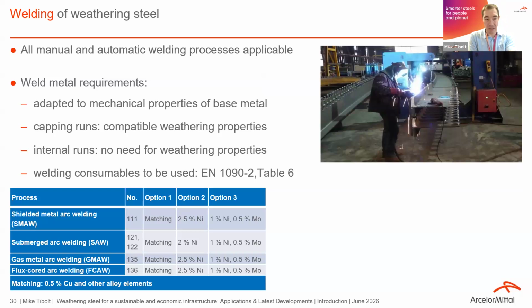Of course, the mechanical properties of the weld metal should be adapted to the base metal. For the outer runs, the capping runs, the weld metal should be compatible with the weathering steel properties. But for internal ones, which are not in contact with the atmosphere, you don't need to have these matching properties. There are weld consumables to be used when welding weathering steel, and this is regulated in Eurocode, in EN 1090 Part 2, Table 6.